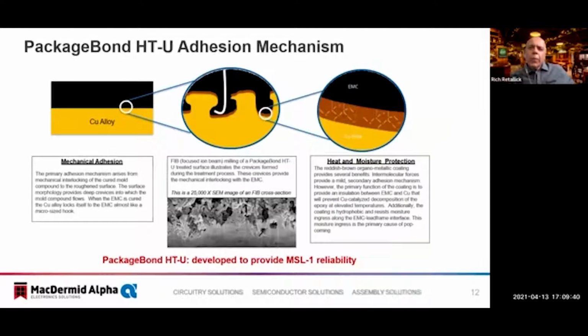The important benefit of PackageBond process is that it enables MSL1 reliability. PackageBond provides both a mechanical and a chemical adhesion enhancement. Mechanical roughening provides a surface into which the mold compound can diffuse, locking the EMC into the lead frame surface. The organic coating associated with this process also improves the adhesion, but it provides a barrier that actually minimizes or prevents moisture ingress. The combination of adhesion and moisture ingress provides MSL1 reliability and prevents delamination. Next.